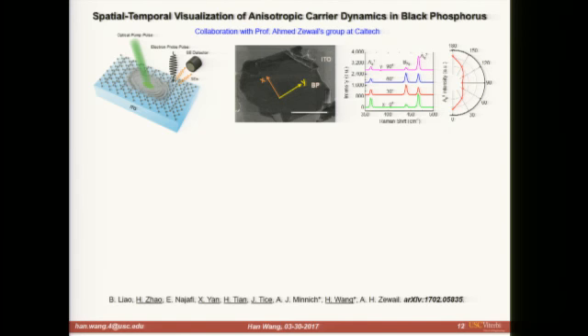So you get a time-correlated signal of the pump laser optical signal and a probe signal, which is the electron beam. The measurement is very similar to the traditional optical pump probe measurement, but the difference is that with this new technique you get much better spatial resolution. In traditional optical pump probe measurements, the spatial resolution of the imaging is limited by the spot size of the laser used to probe the sample, which is on the micrometer scale. With this technique, the spatial resolution is only limited by how good your SEM is - that's nanometer scale resolution, giving much finer details of the carrier dynamics you're imaging.